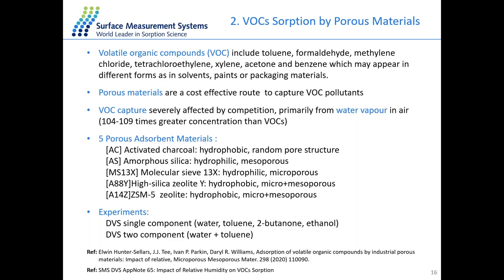It's also very important to consider that in a typical environment where the VOC exists, there will be a much higher concentration of moisture in the air, and how those water molecules will compete for the sites with the VOC type molecules. So that's why we need to do the experiment both with the single component, water, toluene, 2-butanone, and ethanol, as well as the 2-component experiment, water and toluene at the same time.